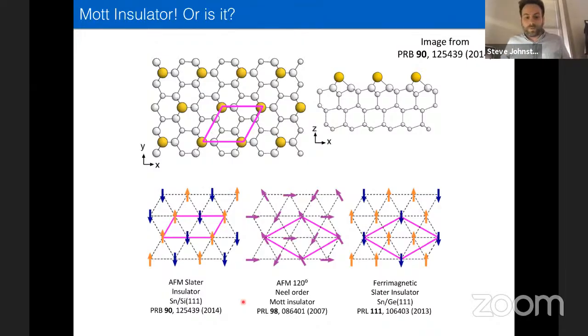There were a number of proposals for different magnetic orders that can be realized in the system. So for example, you can have this antiferromagnetic row-like ordering occurring. There are these spiral 120 degree antiferromagnetic orders that have been proposed. And there have been these ferrimagnetic orders that have been proposed. And this paper here from this PRB was essentially arguing that no, the system's not really a Mott insulator. It's more likely probably a Slater insulator. And the insulating properties are being driven by the magnetism.